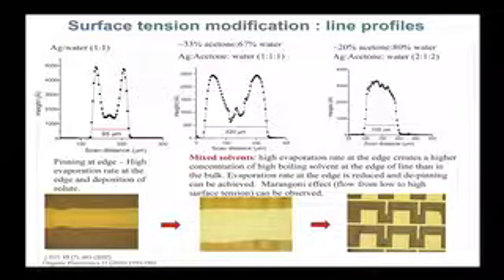So there is another phenomenon that's called the Marangoni effect. And the Marangoni effect basically is a flow that happens opposite to the coffee stain, and it brings things from the edge of the drop towards the center of the drop. And in order to achieve that, the condition you have to have is a gradient in the surface tension of the liquid.